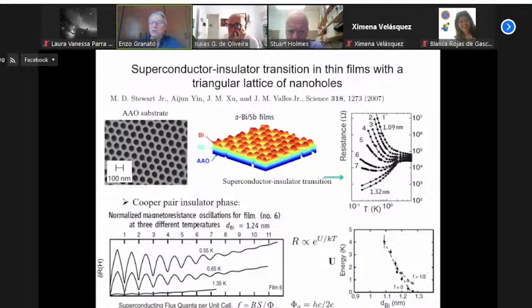In this experiment here, using the nanoholes, they can actually ensure that in the insulating phase you have a Cooper pair insulator. So you can still use a model just for bosons, no fermions around. And this can be done because experimentally, you see in this figure here, the resistivity in the insulating phase oscillates with magnetic field, with the oscillation being the magnetic flux quantum for a Cooper pair, h over 2e. So if it was e, then it could be something different. It could be just an electron insulator. That's a particular thing in this model.